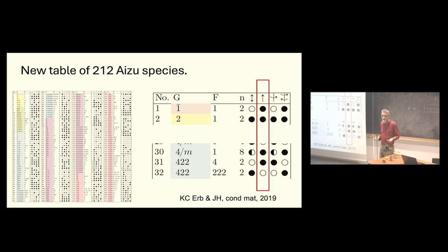It's a very easy definition which allows you to know just by symmetry whether the material is potentially ferroelectric. You just need the point groups of the high symmetry and low symmetry, because ferroelectricity in principle is defined as a macroscopic phenomenon. It's a spatial average polarization. That's why it's possible.